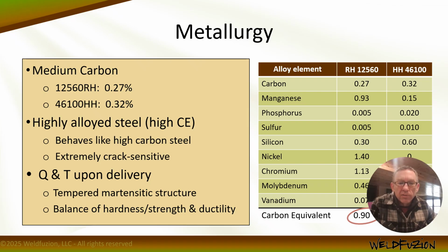As we dive into the metallurgy, as we mentioned, 12560 and 46100 are really at the low end of the medium carbon range. So in the case of 12560, it's 0.27% carbon, not all that high. 46100 high hard has 0.32% carbon. So by AWS standards, we're looking at a 200 to 400 degree Fahrenheit preheat, followed by slow cooling, and we should be able to manage that. However, when we look at the alloy content, the increased alloy content making these things high strength, low alloy, quench and tempered type steels, you're going to see that they behave like a high carbon steel, because the carbon equivalent is actually about 0.90. So we're up really in that high carbon content. They're extremely crack sensitive if we don't follow certain rules and guidelines, right?